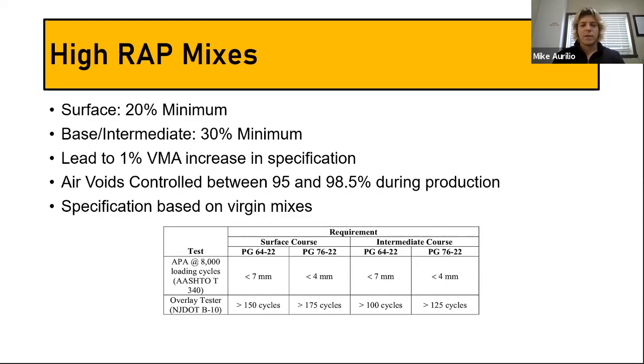And again, the specifications are based on virgin mixes, so you can actually see at the bottom of the screen what the numbers are. And like I said, this comes from the virgin mix database, and their basic premise was we take a virgin mix that we know performs well, we perform these tests on it, we get these numbers. If I want to include RAP, that mix has to have the same numbers or better.